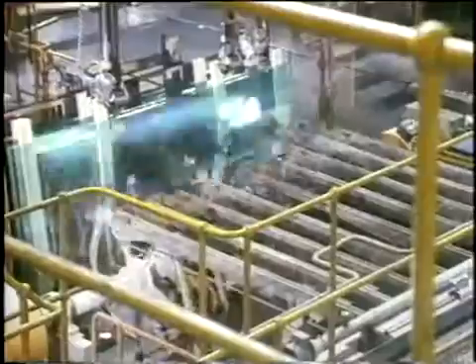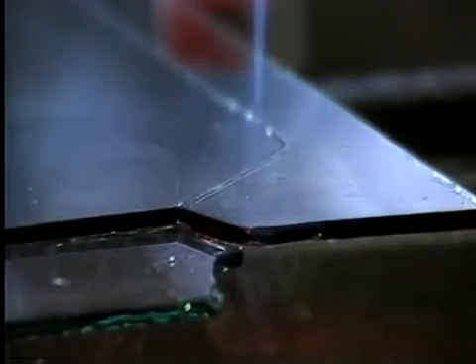Your car windows started like this: sand, limestone and dolomite to stabilize the chemical reaction, soda ash to lower the melting temperature, and broken glass or cullet to help the melting. A continuous ribbon of molten glass is floated on liquid tin before being cut into flat pieces. A computer-controlled tungsten carbide wheel scores the required shape of your car window, and a flame creates thermal stress to crack it along the score.